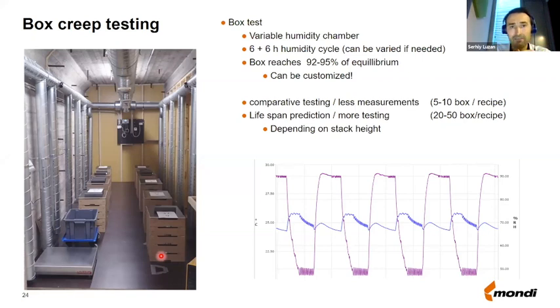the supply chain. Of course, here you can do the prediction of the box lifetime, but you can also do the comparative analysis between different types of boxes. Depending on what kind of tests you will do, you need different amount of samples. So for instance, if you are doing just a comparative testing between different type of recipes, then even 5 to 10 boxes is enough. However, if you would like to really build this load versus lifetime curve, then you need up to 50 boxes per 1 recipe. But in principle, it is possible to predict the lifetime of a box.